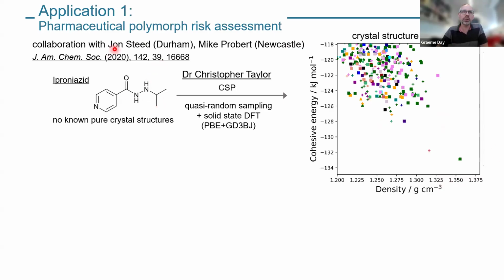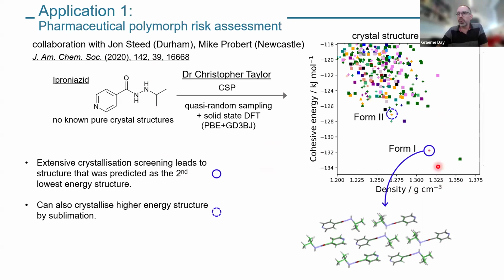And in parallel with our calculations, John was doing some experiments in Durham. What he found is that most crystallization experiments find this one. And this is an overlay. In green and colored by element are the X-ray structure that John found and the predicted structures. You can see that geometrically, we had a very good representation of that observed structure. From a couple of experiments where he did things in an unusual crystallization setup, so rather than out of solvent, he sublimed the molecule and then got it onto a cold surface, you then get a different crystal structure up here. But again, it corresponds to one of our predicted structures.